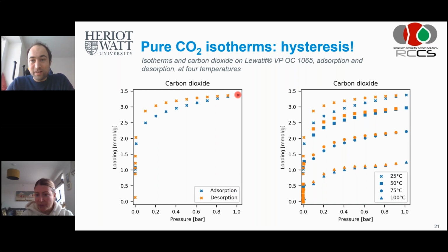I think Connor has got a question as well. Yes, hello. Thanks, Victoria. My one question would be, how regenerative are these materials? So upon multiple cycles of water absorption, CO2 absorption, are you getting similar kinetics and capacities upon multiple cycles? Yeah, they are very regenerative actually, which is maybe a bit of a surprise, and they even tend to perform better in real life than what people had expected after cyclic experiments in the lab. The one problem that you do have is that if you have oxygen and a higher temperature at the same time, then the amino groups will degrade. But you can engineer that out.